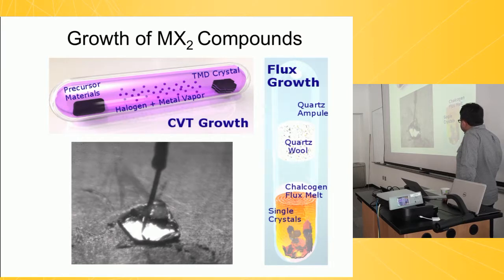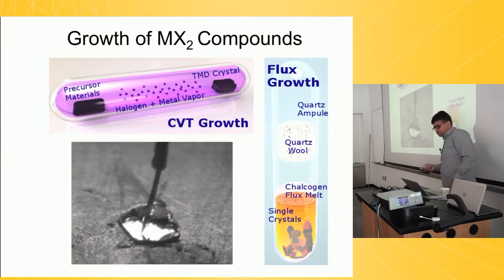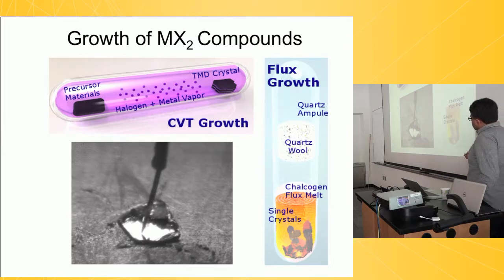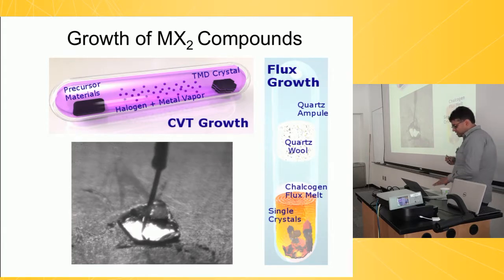And then you seed a little crystal, and you just let it grow, and you let it get bigger over time. So that's the second method that we've adopted. And at the end of the day, we have nice shiny crystals, and we want to study them in as pristine a form as possible. So we put them in a UHV chamber. We cleave them in situ so that we have no external impurities, and we come down with an STM tip, and we want to see what kinds of defects we have.